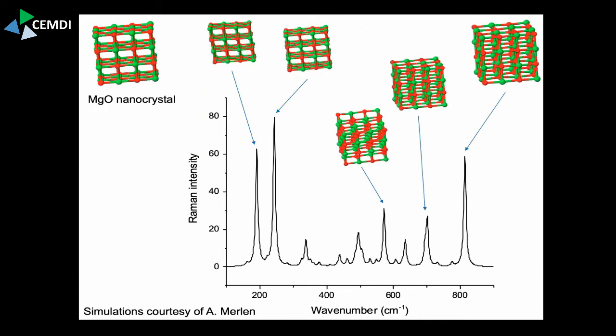So what we then did, respectively, what Maria and Alexander did, they calculated magnesium oxide nanoparticles, or things alike that could happen on the surface. You see these shearing modes. This is actually a radial breathing mode, and you have some higher order with a higher frequency. And you see these modes are actually Raman active. You may know this from carbon nanotubes. Radial breathing modes are also Raman active there, but they should be strongly damped if the particles get bigger. But in magnesium oxide nanoparticles, there is good reason to believe that they should be Raman active.